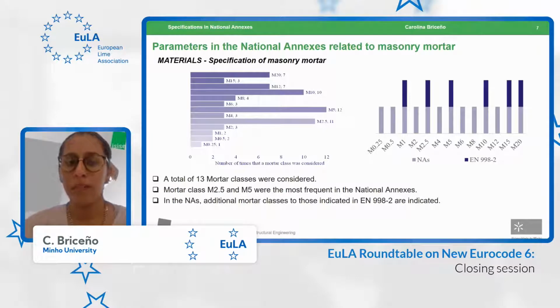Regarding the mortar classes, in total, it was possible to identify 13 mortar classes, where the mortar classes 2.5 and 5 were the most frequent in the national annexes. Also, Eurocode 6 Part 1.1 recommends those mortar classes indicated in the standard 998-2, which are the ones shown in blue in this graph. However, we see that in the national annexes, there are additional ones, as the ones shown here in gray.